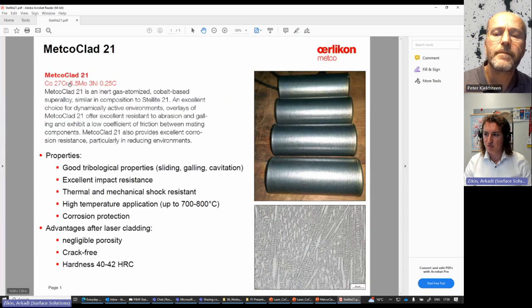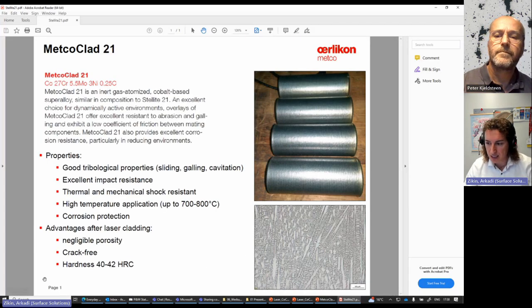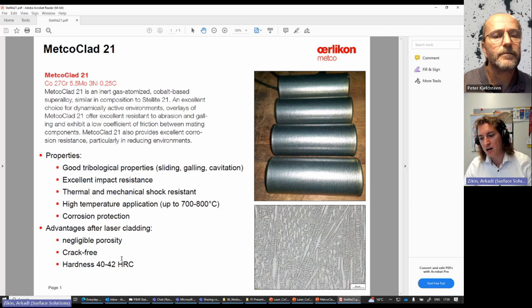So if you see here the 40 microns, the dendrites are pretty small, which gives many dendritic alloys like stellites higher hardness values directly after deposition. So you get better overall properties. The Hall-Petch effect shows here that with finer particles or finer grains, you get higher hardness. Correct. And you also get better corrosion resistance because you have many more grain boundaries.